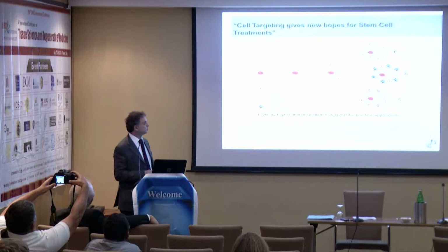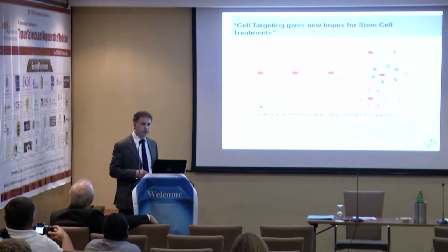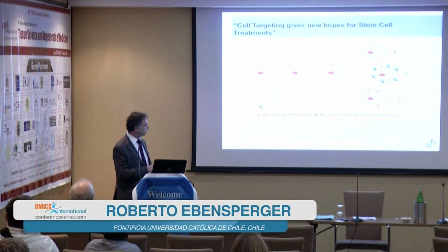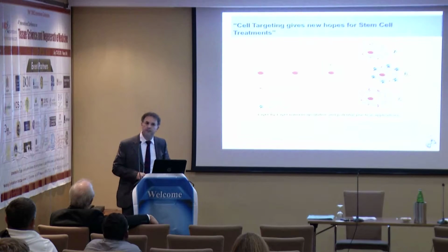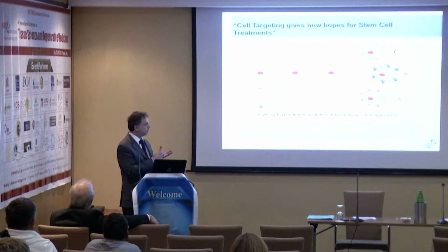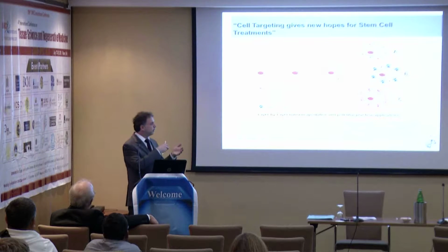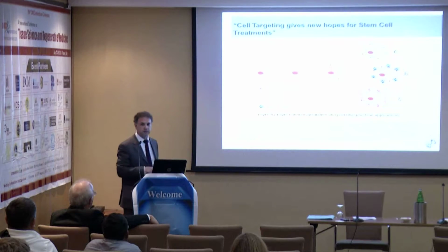The nanoencapsulation that we have done is not a new method. It's a very well known and old method called layer by layer. If you put a lot of layers over the cells, you can immuno-isolate the cells, for example, against the recognition of antibodies. The layers that protect the cells can block the antibody from entering or coming in order to recognize a specific protein on the cell surface.